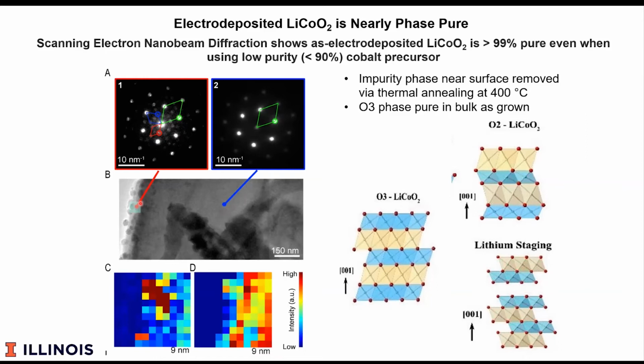And that's a problem because remember, it's the very surface that the lithium ions have to come into. If the surface has the wrong crystal structure, it may act as a barrier and inhibit the transport of the ions. Fortunately, we found that if we anneal this in a slightly oxidizing environment at about 400 C, then this phase grows out. Probably there's some sort of recrystallization from the bulk, because this is only on the order of a few tens of nanometers thick. So by annealing, we're able to remove that surface phase.